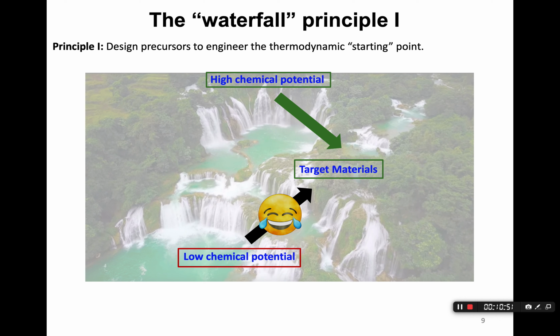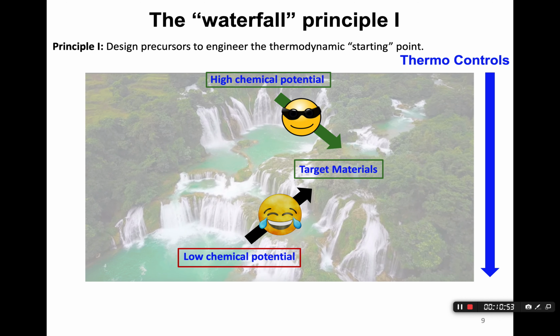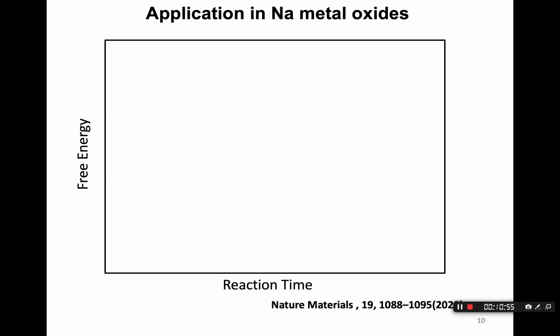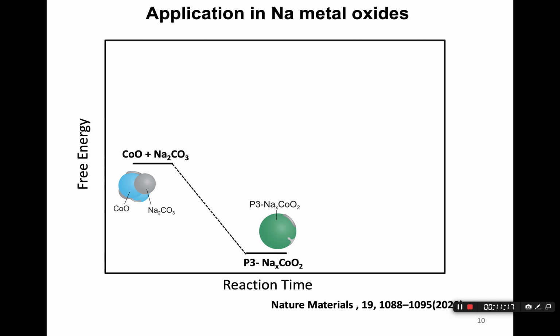So let me then give you an example of a real case. In this Nature Materials paper published in 2020 by my colleague Jin Yang, he actually tried to make a sodium metal oxide, which is frequently reported and studied in the field of sodium-ion batteries. So typically, we mix a cobalt oxide with sodium carbonate, and they're going to end up with a P3 sodium cobalt oxide. This is usually the first phase you see when you do a solid-state synthesis.